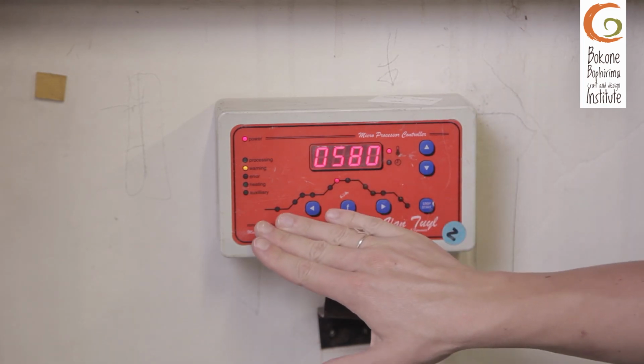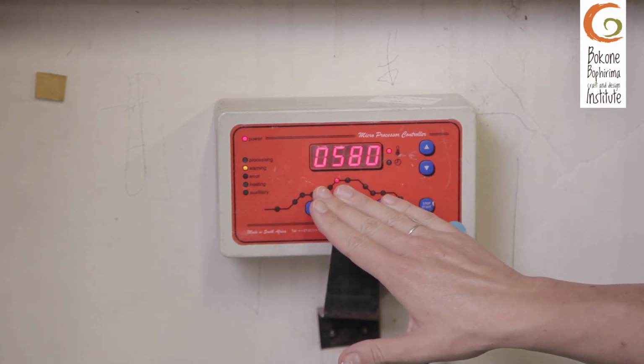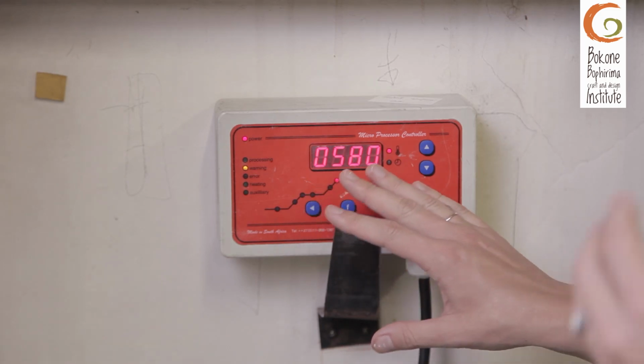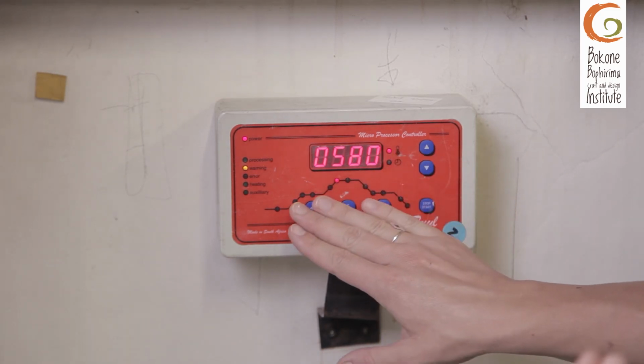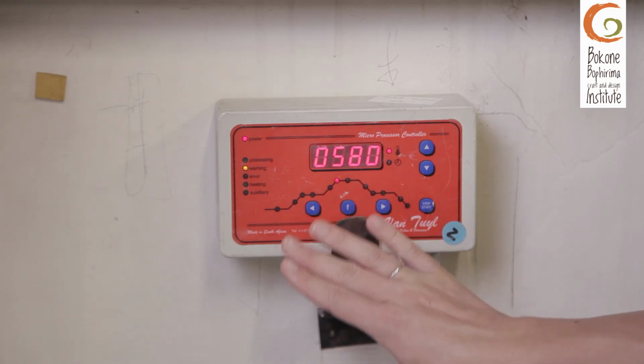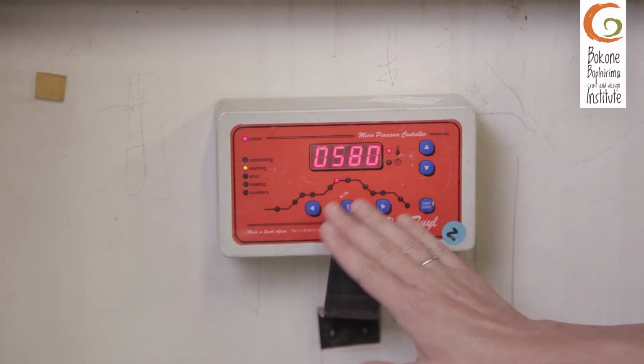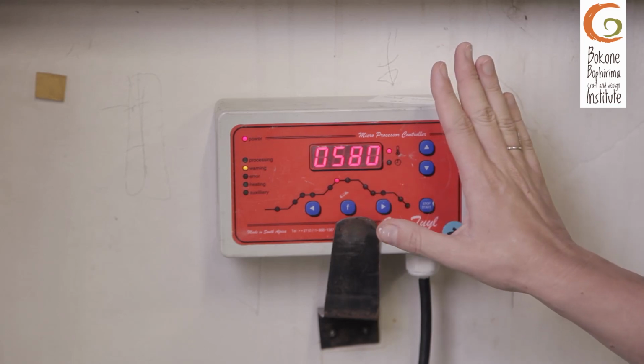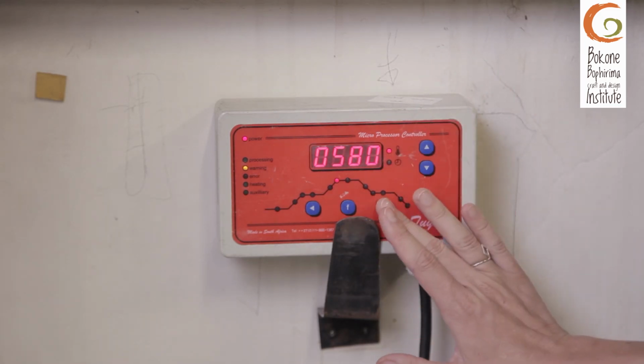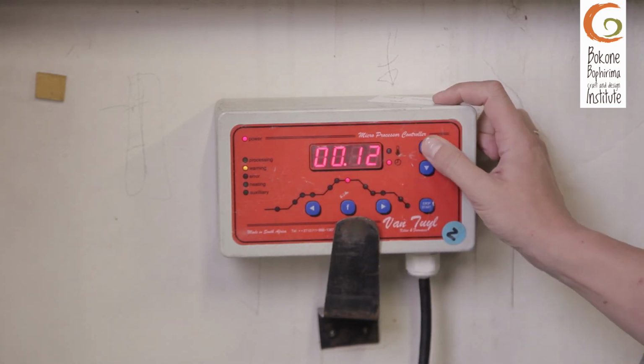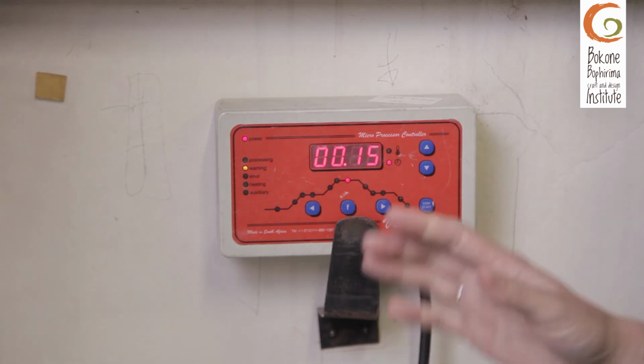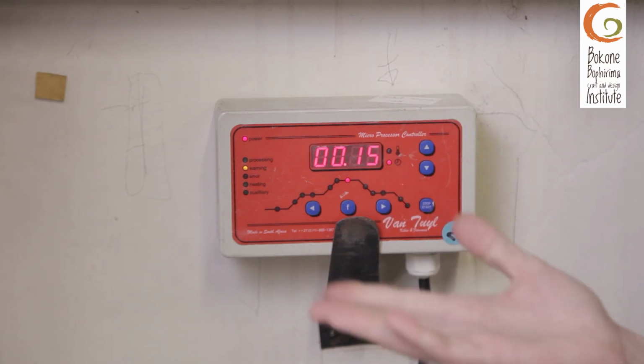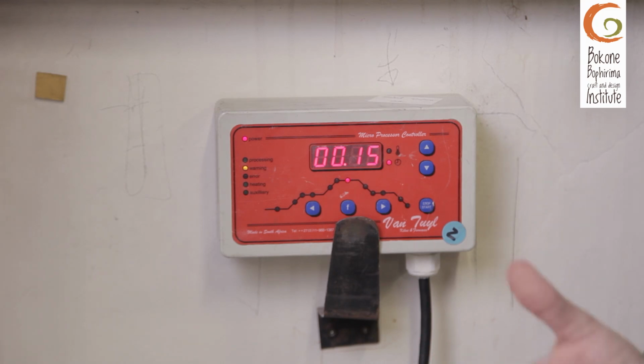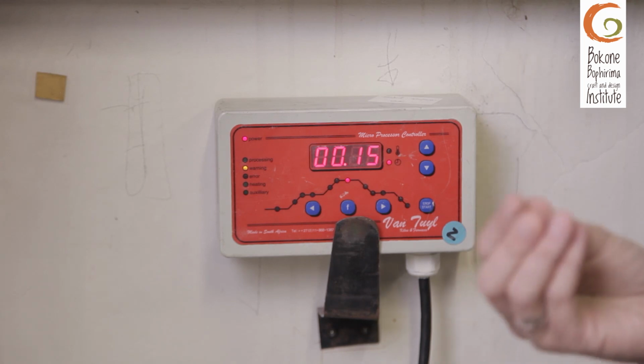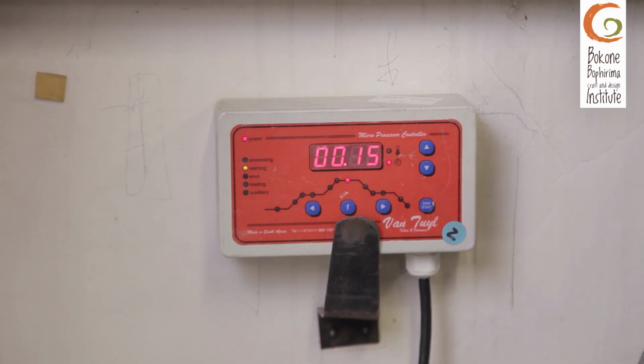Okay, so I didn't take my time at 300 because I don't need a delay there. Our glass is at quite a critical point. It's got a lot of tension there, so we're rather going to pass through and we're going to keep ramping up, but at a slightly faster degree temperature, up to 580. And then we're going to hold it there for 15 minutes to ensure that our glass powder enamel paint has made proper contact with our glass surface. They don't fuse together because it's not high enough temperature, but has melted on top of the glass and